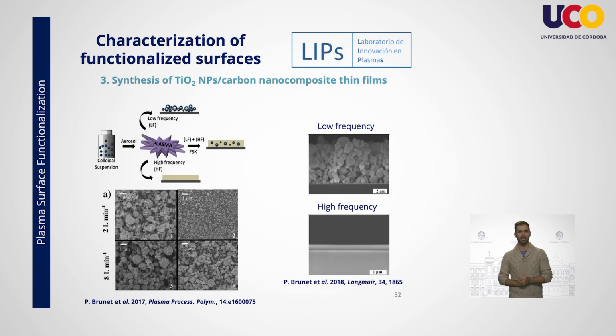Finally, in this last work, the synthesis of titanium dioxide nanoparticles and carbon nanocomposites by DBD is discussed. In my opinion, the results found here are particularly interesting. Why? Well, as we will see, from the same system and precursors, and depending on the parameters used, we can obtain either a thin layer of carbon, a coating of titanium nanoparticles, or a nanocomposite formed by the nanoparticles inside a carbon matrix. For this purpose, a solution of titanium dioxide nanoparticles was prepared in isopropanol.